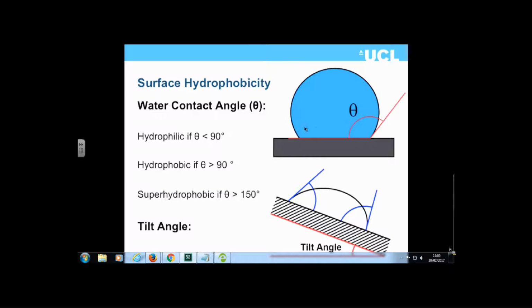It's hydrophilic if the contact angle, well, in some definitions less than 60, but the one I'm using if it has a contact angle less than 90. And it's superhydrophobic, similar to the structure we showed with the ant, if the contact angle is 150 degrees or greater. Now there's some other angles which are also important for these superhydrophobic surfaces.